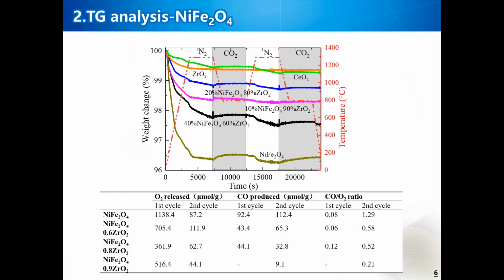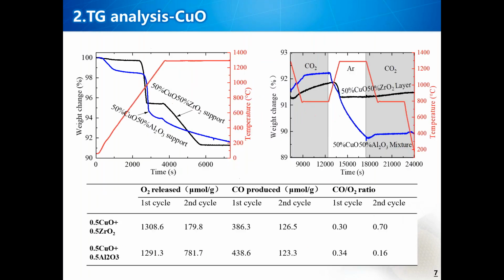And 20% nickel ferrite and 80% zirconia can make the unit mass nickel ferrite reduce more CO2. And CeO2 is often used as a catalytic material for electrothermal chemistry and has a strong ability to release oxygen.